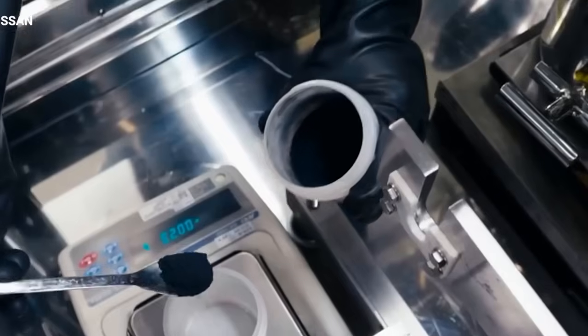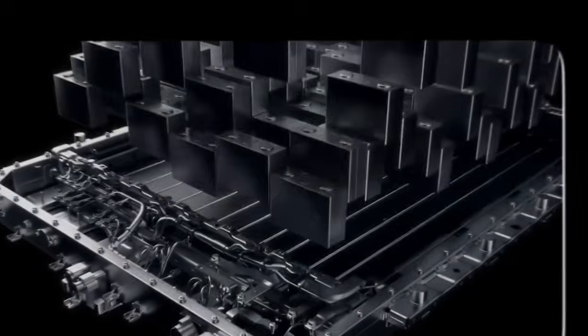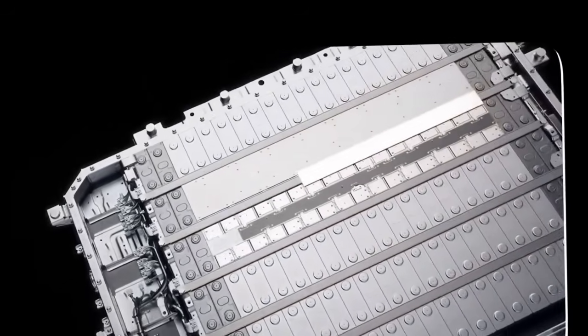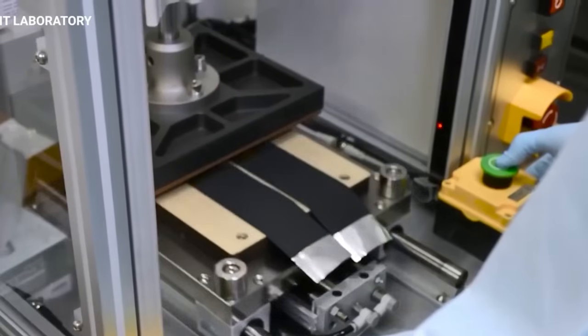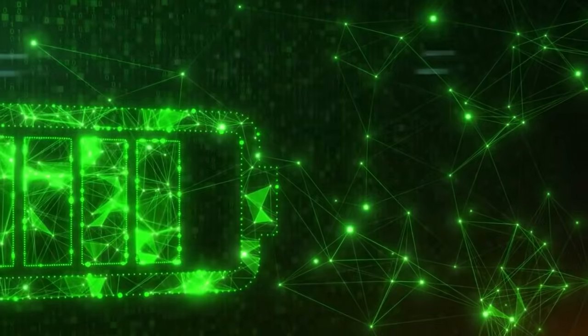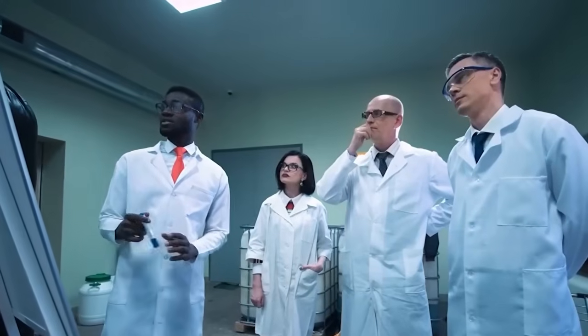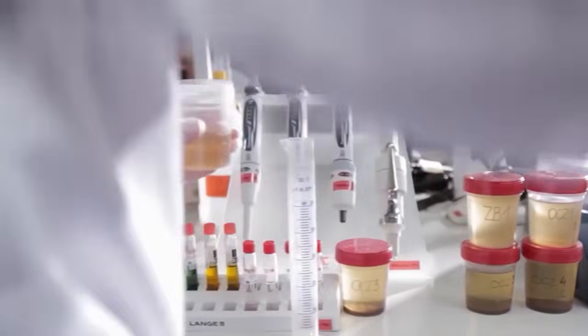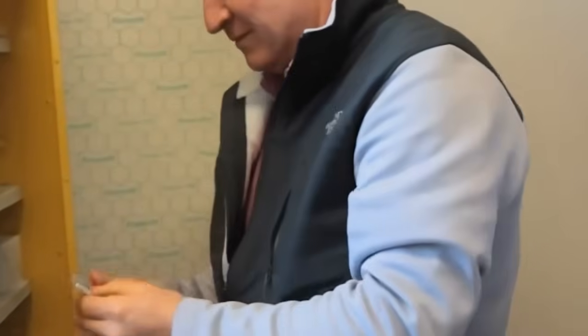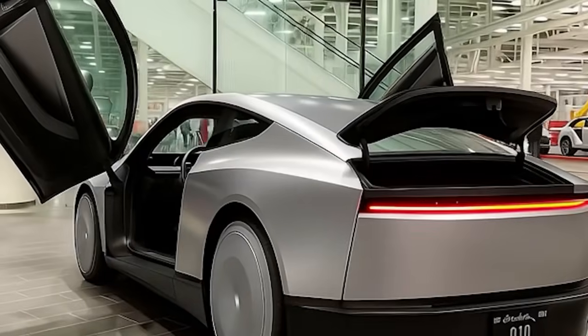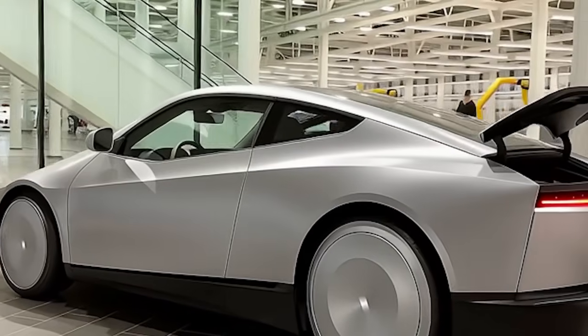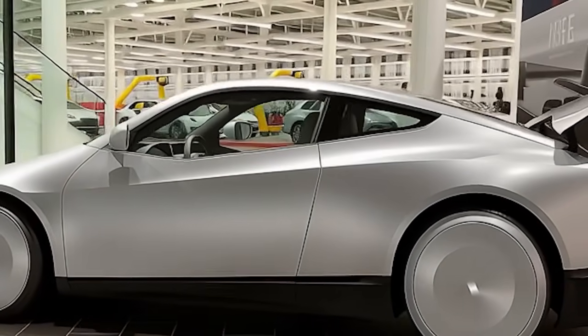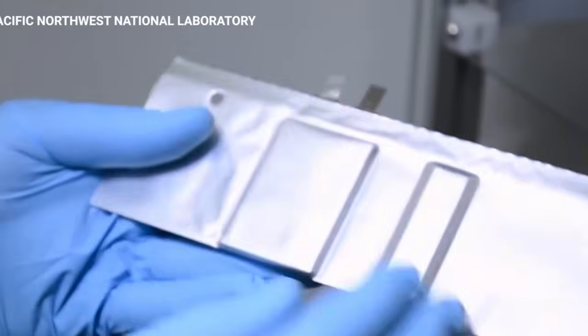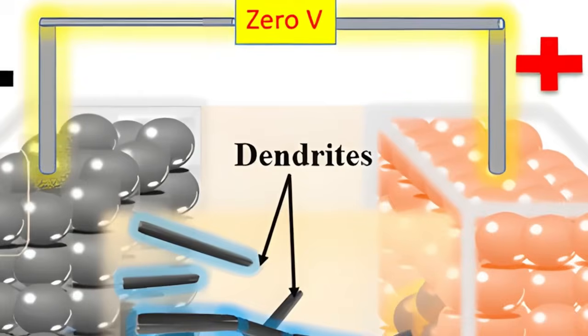costs of EVs. How does a lithium sulfur battery's energy density outperform that of a lithium-ion battery? According to the research, a 4,680 cell's energy density was 244 watt-hours per kilogram. In contrast, the energy density of the sulfur battery will be around 723 watt-hours per kilogram. What does that actually mean in practice? Well, for instance, if you were to swap your EV lithium-ion battery with a lithium-sulfur one, you could drive your car roughly 3 times longer without needing a recharging station. Or you could keep your existing range with a much smaller, lighter, and cheaper battery pack.